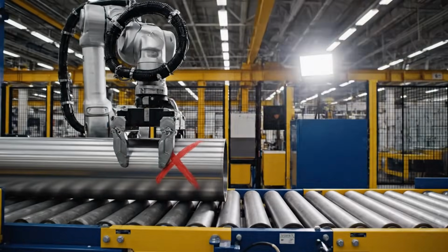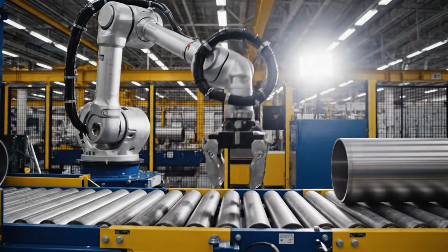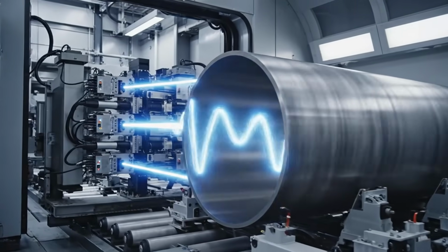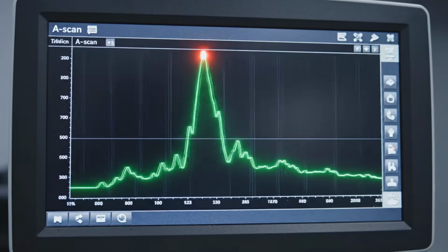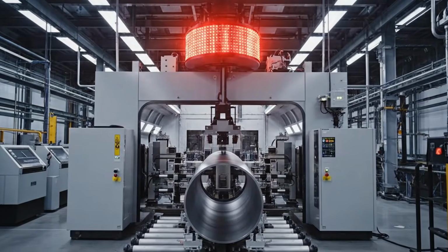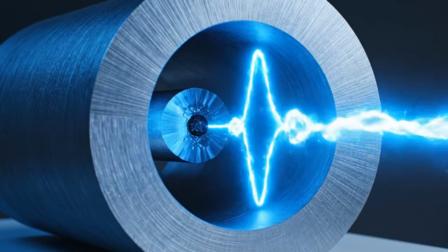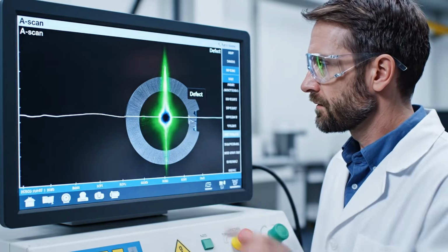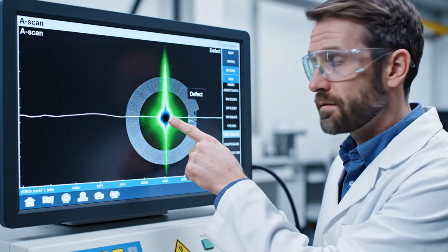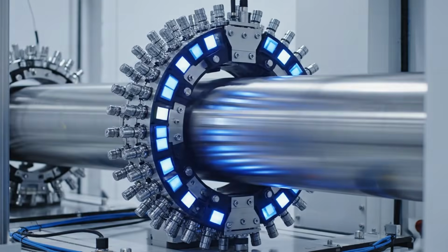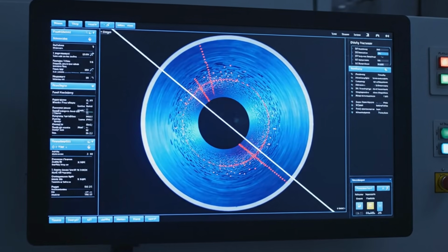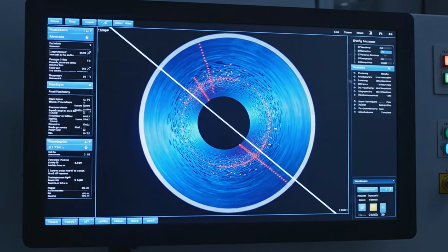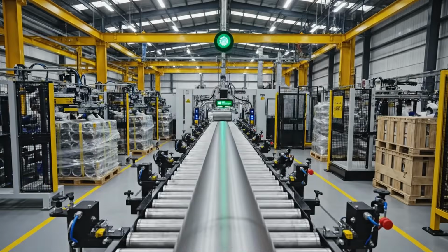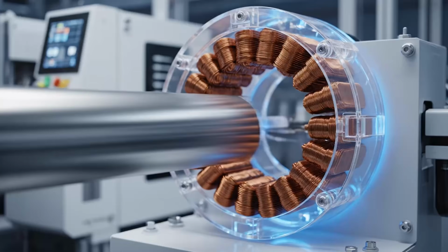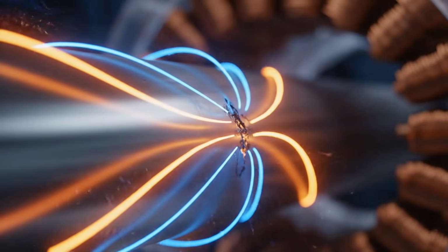A tube that looks correct from the outside can hide an uneven wall. In pressure service, that inequality concentrates stresses and reduces the safety margin. Then comes the surface inspection. Cameras, sensors, or assisted visual review detect folds, adhered scale, roller marks, longitudinal cracks, deep scratches, or open laminations. Some minor defects can be removed by localized grinding, provided they do not compromise minimum dimensions. Others imply direct rejection. Seamless tube is sold precisely for applications where the material must inspire confidence, not doubts.